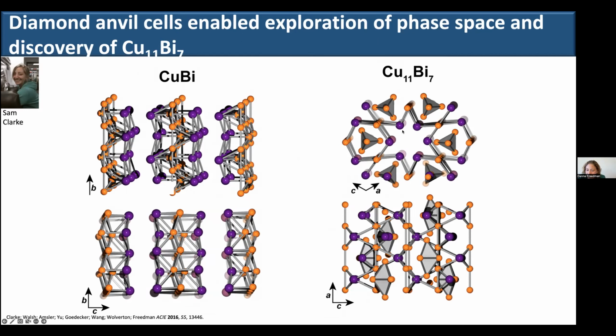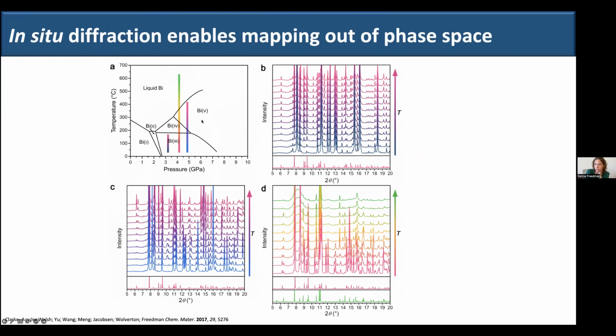For example, if you see these aren't technically channels because they're not porous, but the columns, which I'm going to assume you can see my mouse. The columns that are formed by these 6 bismuth atoms, you can see that the arrangement of them is very much supported by the protrusion of lone pairs into this non-channel structure, into this column. And another feature, which to me is fairly notable, is that the bismuth and copper local structures segregate into more bismuth-rich regions and more copper-rich regions. We also have this copper-bismuth 1-to-1 binary compound. I don't know why that happened. Okay.